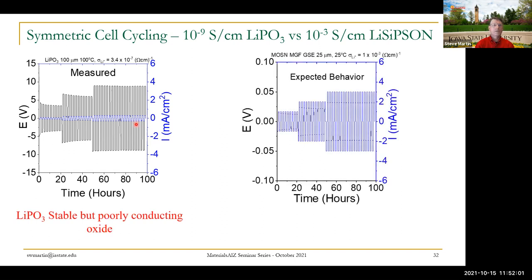So where are we looking long-term? This is the behavior I just showed you. Many volts required to drive the even microamps of current that we get. Now this data I'm about to show you is not experimental data, but this is our expected data. That if we have, instead of a 10 to the minus 7 conductivity of LiPO3, rather a 10 to the minus 3, then everything's reversed.